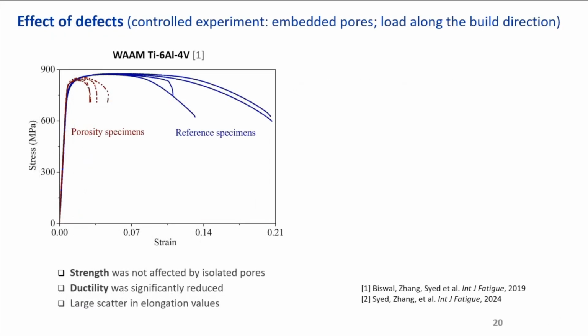We also found this in our own research, in the wire arc Ti64, and the blue lines are the reference specimens, no defects. The dark red curves here are purposely built defects, so we have a control. We just have one or two, but we know they are porosity specimens. The conclusion bullet point is that strength is not affected by isolated pores, but ductility suffered significantly, which I will discuss why. And there's also very large scatter in additive manufacturing materials, even without the defects. So I will talk about this.